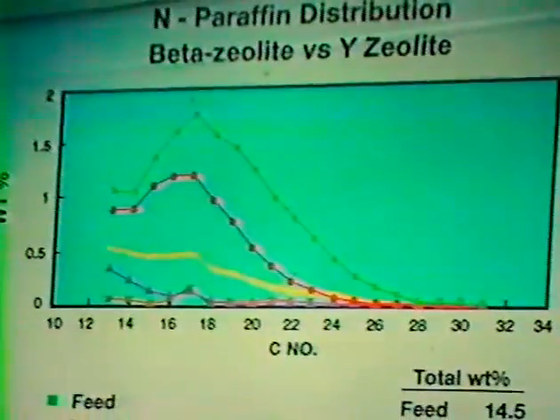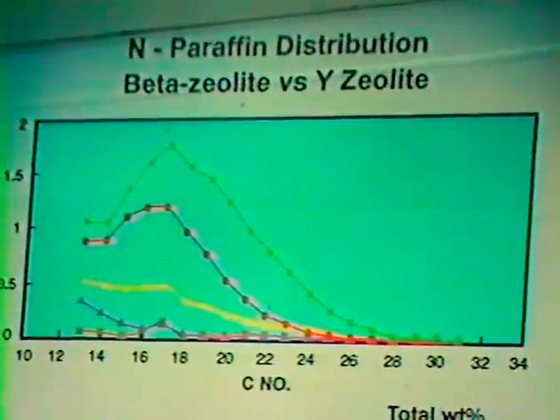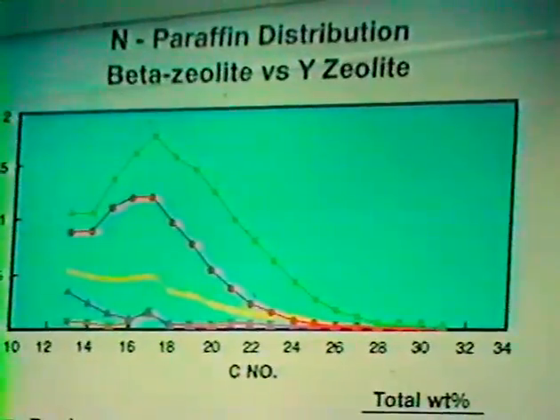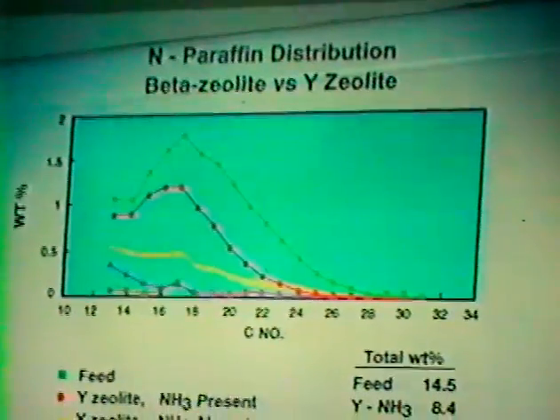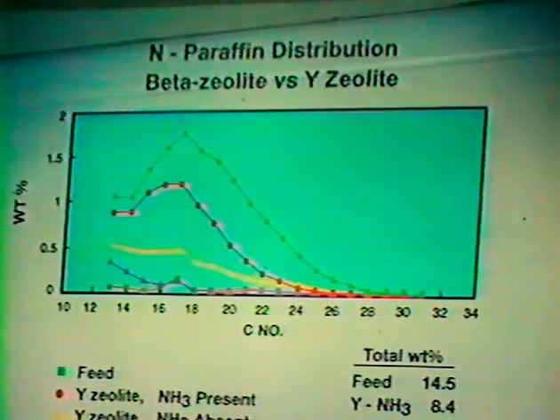If we use beta-zeolite instead, we produce much less normal paraffins compared to Y-zeolite, or total is down to 1.2 in one case and 0.4 in the other case. So there's something fundamentally different going on in the cracking mechanism in these zeolites. We've had a couple of guesses what it is, and we feel there might be some illustration of the structure.